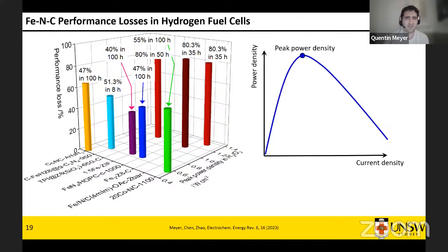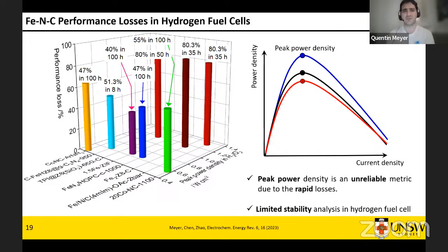What I mean by that is if you capture a polarization curve once, this is the power you get. You capture it immediately afterwards, you may have lost 10%. And in the first hour, you may have lost about 15 to 20% performance. So as a result, the metric we all use, peak power density, can be quite unreliable because the loss is so fast, which means you captured this probably as fast as you could to get to peak power and immediately capture it. And as well, this is rarely published in papers, how many times people have tried before they got the peak power they're reporting.